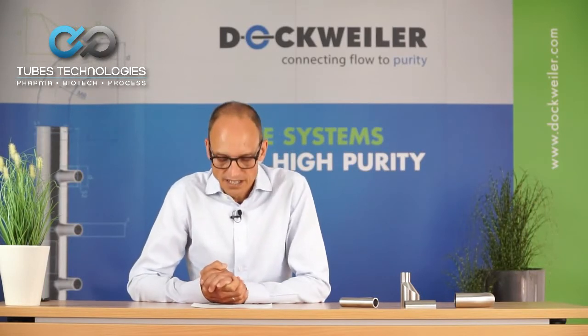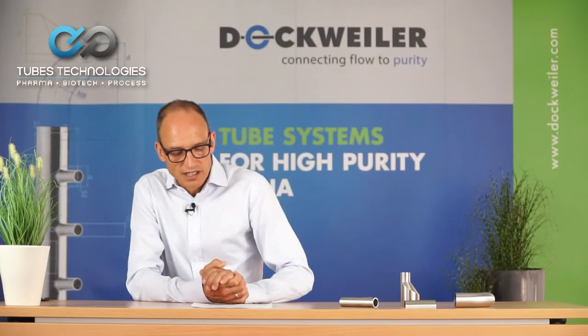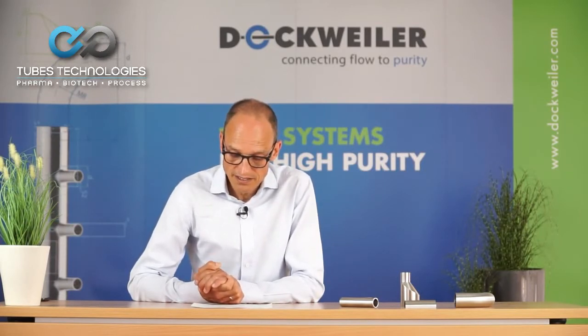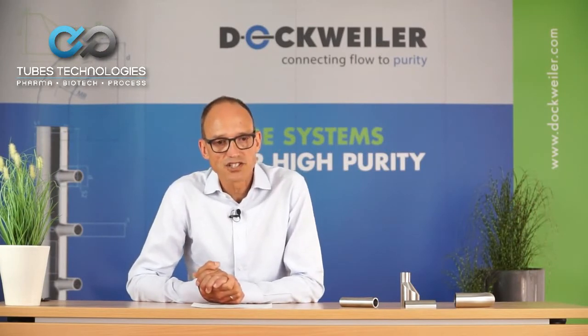Examination and inspection shall be done on a sample basis. This is also defined. So with 100% visual inspection, there is a sampling of Ra, ID, OD, dimensional check, ferrite measurement if specified. This is an option only. Marking needs to be verified. And documentation is pretty much a COC or an inspection certificate 3.1 according to EN 10204.